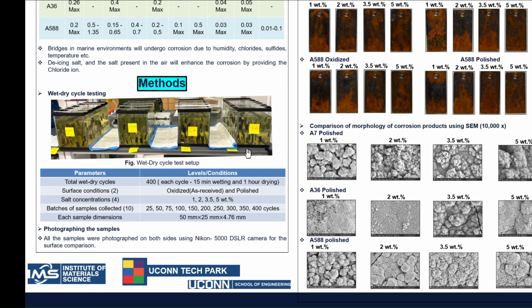We used the wet dry cycle testing method as is shown in the figure. We took water tanks of 10 gallons in size each, and each tank is designated for a specific salt concentration, and four salt concentrations were used: 1, 2, 3.5, and 5%. And two surface conditions of the samples were used: oxidized and polished.